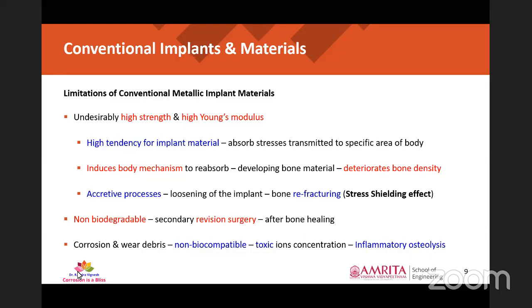So that will release toxic ions in the vicinity of the implants that will lead to inflammatory osteolysis, which means there will be a bad response from the tissues that are surrounding the implants. So these are the negative things that come into the picture when we have conventional metallic implant materials with undesirably high strength and high Young's modulus. Okay, so this creates the need for development of materials with good strength equivalent to that of bone and Young's modulus equivalent to that of bone, so that we don't end up with stress shielding effect or inflammatory osteolysis.